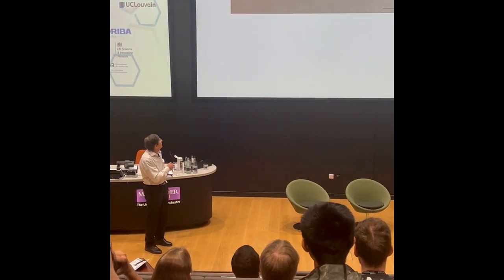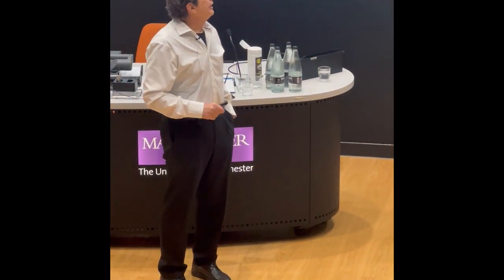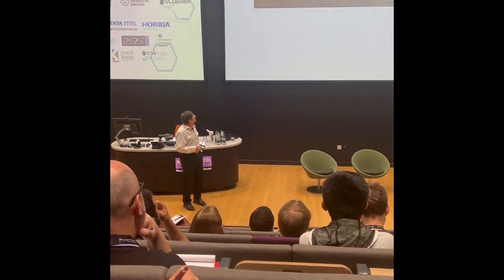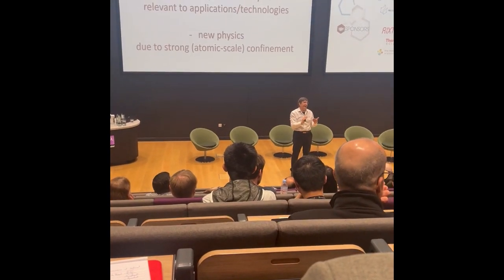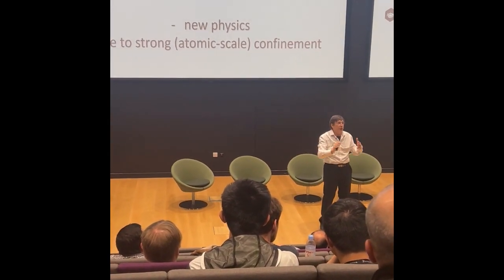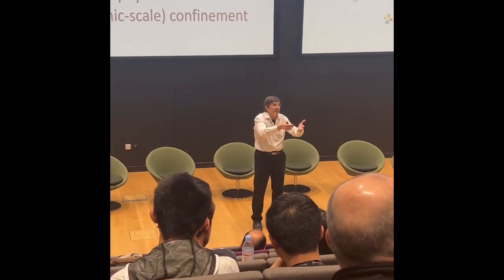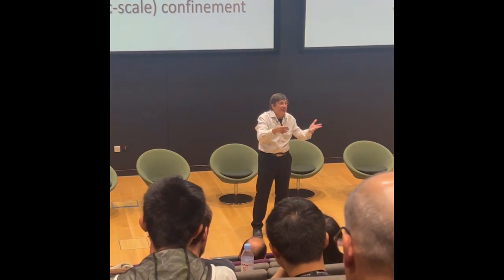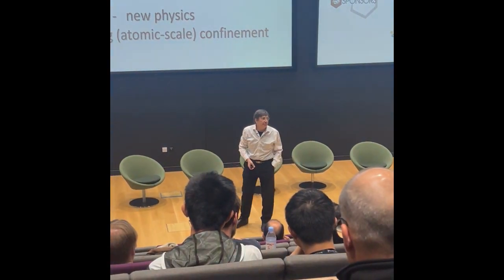Here you see a slit, and this is only a 2.7 angstrom capillary. This is graphite, this is graphite. Essentially, this is 2 planes pulled out of graphite, as I told you, although it's done by assembly. We never managed to get a decent photograph for a monolayer. If you wish, not only absorption but also intercalation works. I said this important word, absorption. This is why water goes there. So this is the simplest qualitative way to explain.